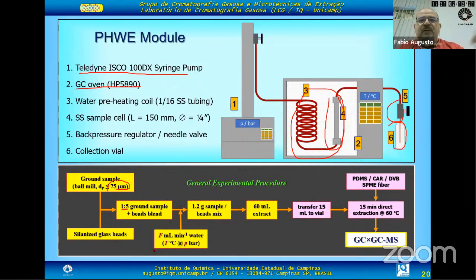We pass water for some time at temperatures and pressure that we optimize, and we'll describe the optimization further on. We collect 60 mL of extract, transfer 15 mL to a vial, and extract it with this triple fiber, PDMS, carboxen-divinylbenzene SPME fiber. It is commercialized by Supelco and has three sorbents, two solids and one polymer. It's very efficient for a series of analytes. We do a 15 minute extraction at 60 degrees, and then we chromatograph it.